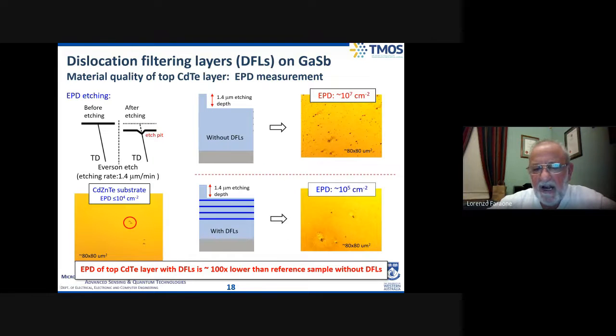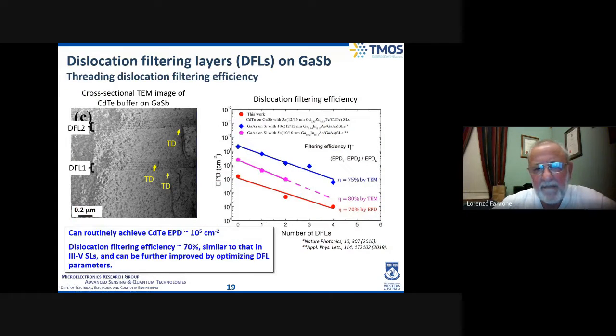We have shown, and other people have done this with III-V semiconductors on lattice mismatched substrates, but we're the first ones to have done it on II-VI semiconductors for infrared imaging devices. You can see that we're able to reduce the etch pit density by about 2 orders of magnitude by using these dislocation filtering layers. Still not good enough, we're only just getting around 10 to the 5 per centimeter squared. So there's still some work to be done there.